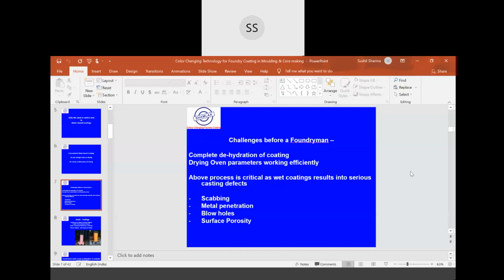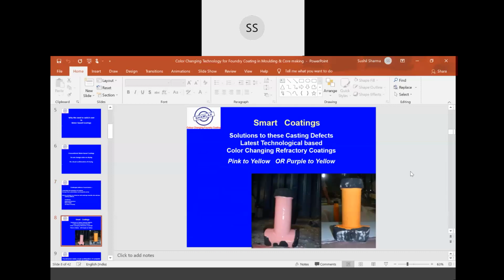The above process is critical as wet coatings result in serious casting defects like scabbing, metal penetration, blowholes, and surface porosity. And at such times, these color change coatings play a major role, which gives a visual confirmation for the foundryman to understand whether the coating has really dried or not. We also call these coatings smart coatings because today we are in an era of smart appliances like smartphones, where smartphones have already replaced the conventional mobile phones. So these smart coatings are solutions to these casting defects, and latest technology based color changing refractory coatings.